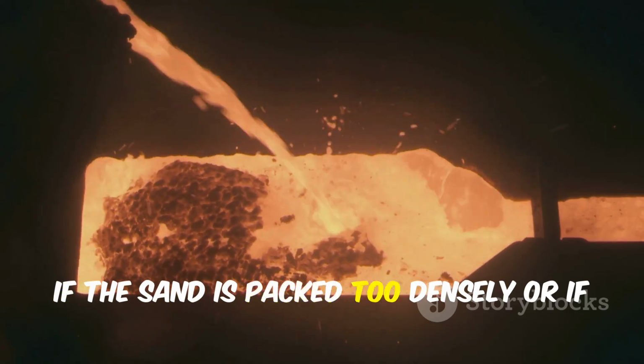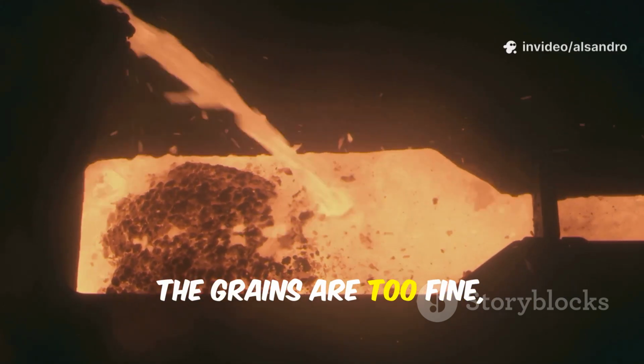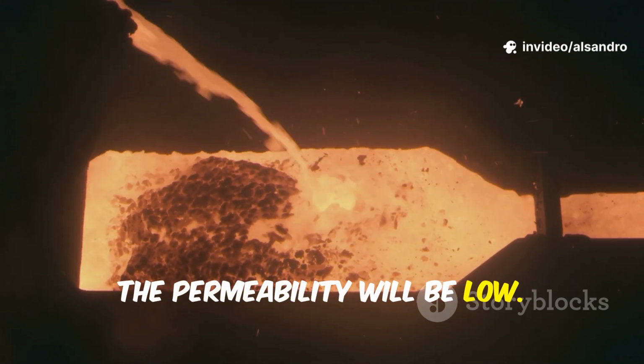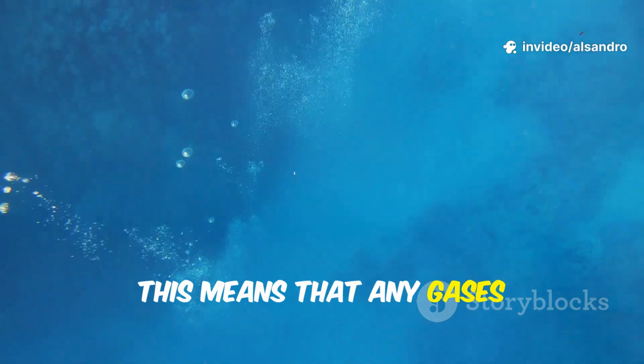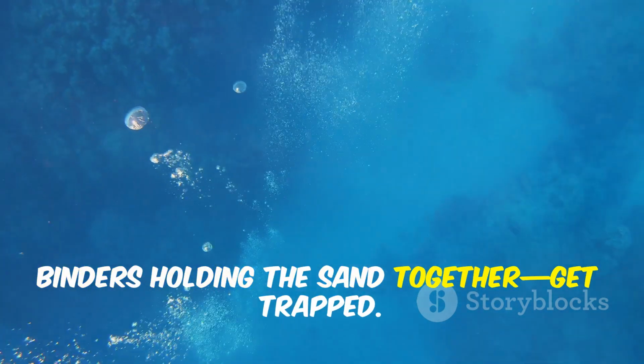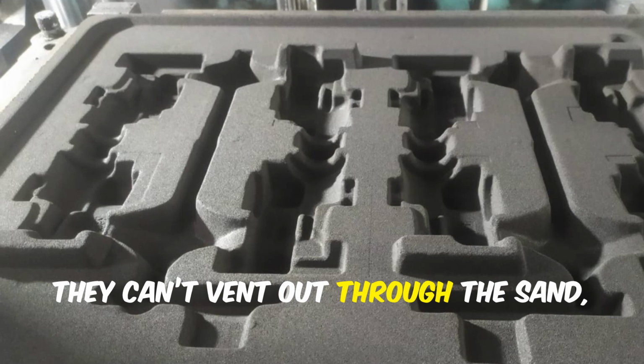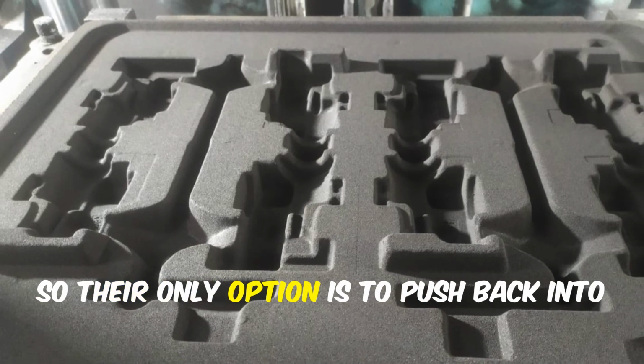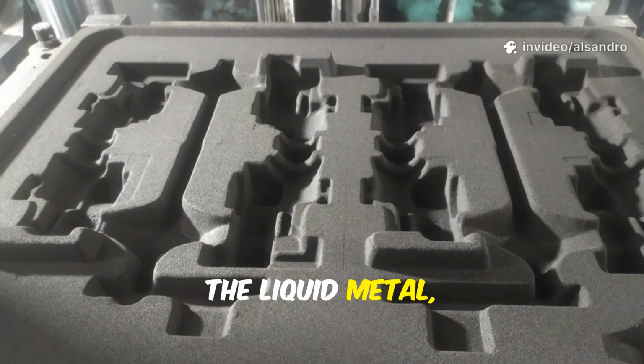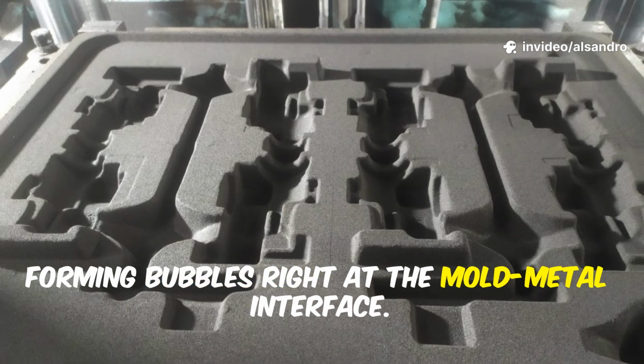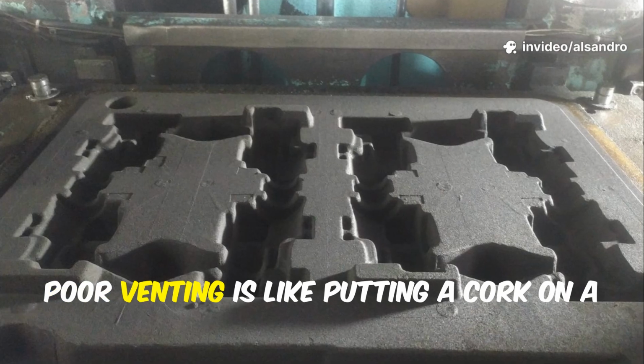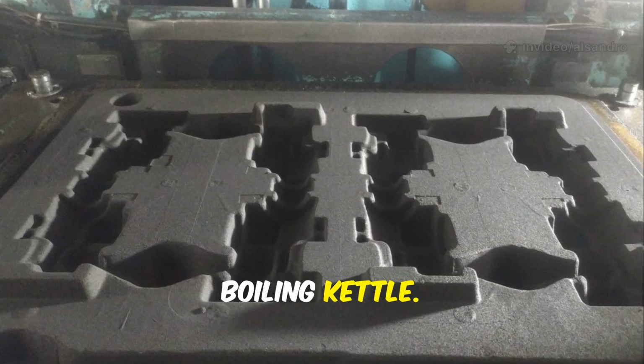If the sand is packed too densely, or if the grains are too fine, the permeability will be low. This means that any gases produced, whether from moisture or from the binders holding the sand together, get trapped. They can't vent out through the sand, so their only option is to push back into the liquid metal, forming bubbles right at the mold metal interface. Poor venting is like putting a cork on a boiling kettle.